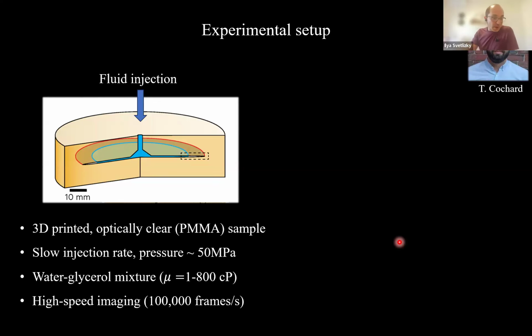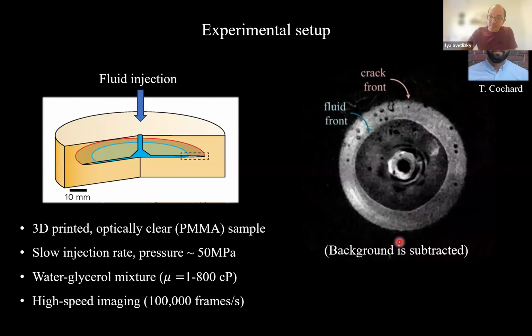And the most crucial part is that we visualize the dynamics of this crack by using extremely high frame rate, about 100,000 frames per second. So this is a snapshot of the measurement that Thomas acquired. We subtract the background, so you only see the changes. The first circle is the propagating crack front. The second circle is the expanding fluid front.